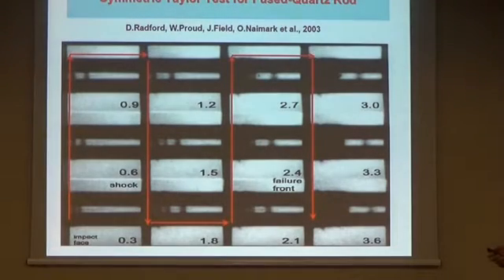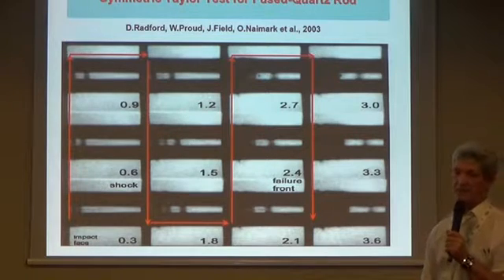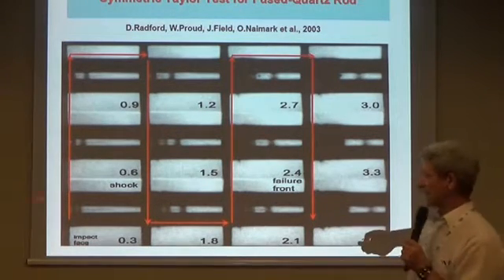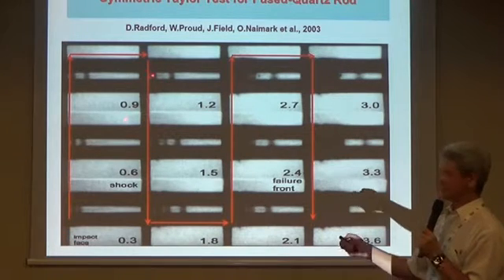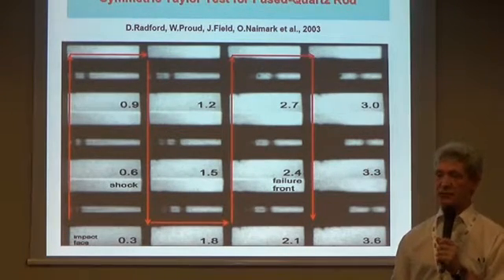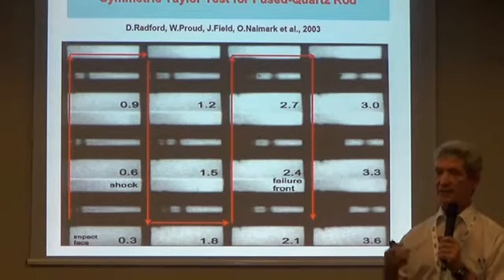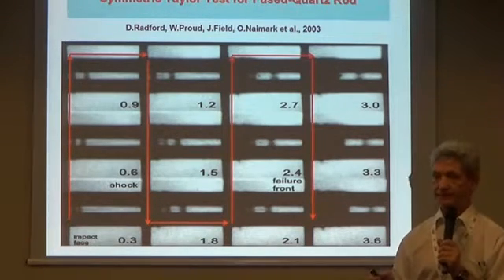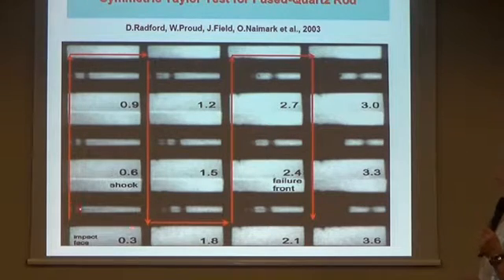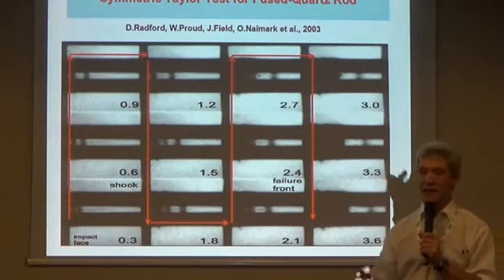To confirm these results, we carried out, together with the Cavendish lab, the following experiment. A fused quartz rod was accelerated up to 500 meters per second, and after collision with the wall, it was triggered with high-speed framing with resolution close to 10 million pictures per second. You see that we saw the stress, and then with some delay there is a dark area which represents the area of the failure wave. It's in this compression stress.